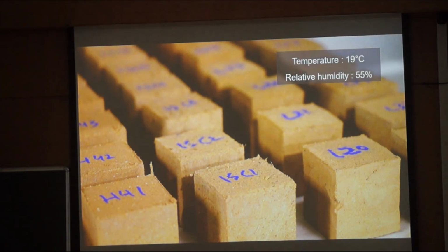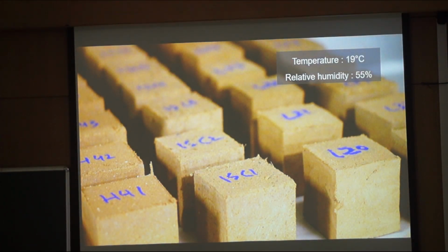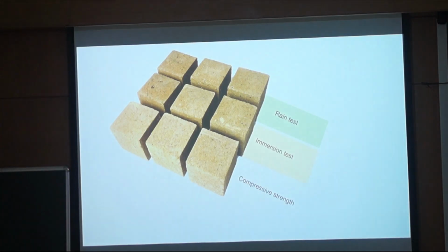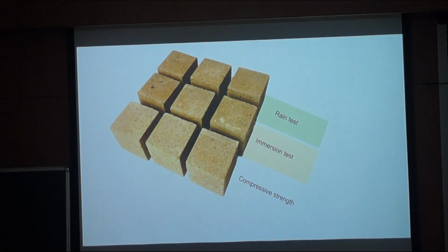These blocks which you saw were kept in a room which had a temperature of 19 degrees Celsius and 55% humidity, because these parameters really matter in terms of strength development and water resistance of these blocks. And after they were dried, I dried them for 14 days. I use 3 samples each for different tests. Strength test, and there are 2 sets of water resistance tests.